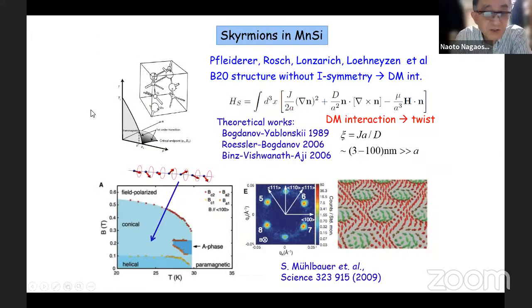And this skyrmion structure was first discovered in the chiral magnet, manganese silicide. So in this chiral magnet, because of the broken inversion symmetry, the Dzyaloshinskii-Moriya type interaction is allowed. In the continuum approximation, this is given by the second term, n dot rotation n. And D is the Dzyaloshinskii-Moriya interaction. J is the ferromagnetic exchange interaction. And the size of this Dzyaloshinskii-Moriya interaction leads to the twist of the spin and the noncollinear spins. And the length scale of this structure is given by the J over D ratio.